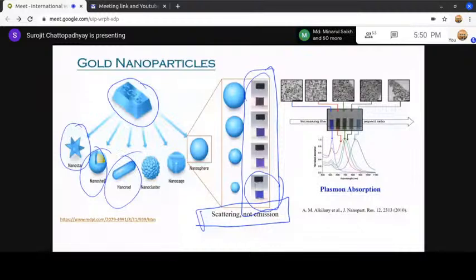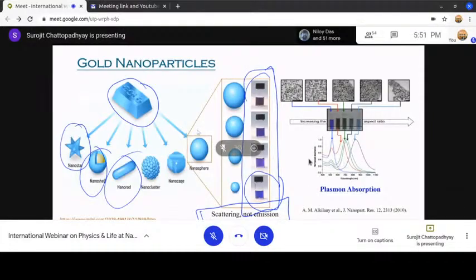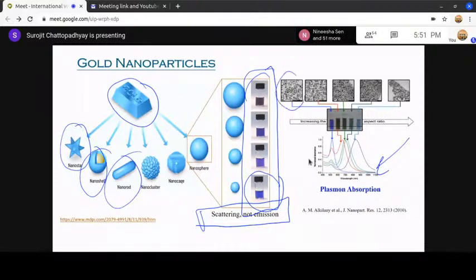The question is, will these gold nanoparticles react to light? That means, will they absorb light or do something with light? Of course. So you take these small bottles of colloidal solutions of gold, and you try to measure the optical absorption. What you see is over here. If you have a gold nanoparticle, you see they have an absorption, this red line, which is near 520 nanometers. And if you take gold nanorods, which are over here, of different length, of course, you can see there are two modes of absorption. One remains at 520 nanometers. The other one shifts to the IR side. For example, this very long nanorod has the second mode at about 850 nanometers. So they have two modes.